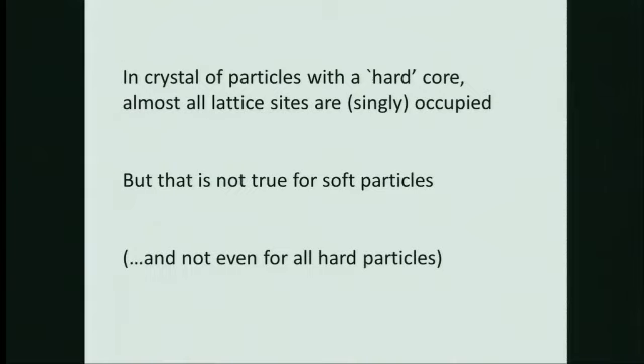I have to go back a bit and talk about how you fill a lattice and what a crystal actually is. Because if you have a crystal of particles with a hard core, it doesn't have to be completely hard, but sufficiently repulsive core, then this could be, I don't know, indeed a colloidal crystal. It could also be a metal or something like that. Then under normal circumstances in equilibrium, you fill effectively all lattices. Not all of them, because there are vacancies and there's also interstitials. But if you have soft particles, that is not true. And actually, as you see at the end, it's not even true for all hard particles.